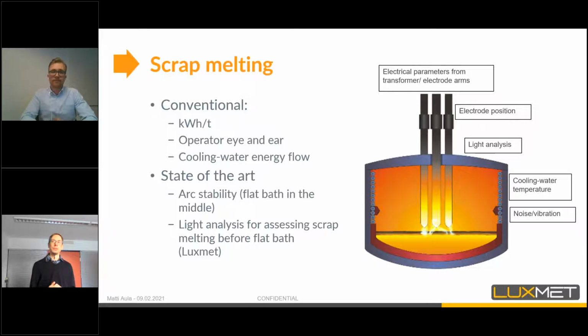Yeah. And also, the state-of-the-art methods, or the best available systems, let's say, many people use these arc stability parameters to assess the scrap melting in the furnace. Because in the flat bath phase, the slag surface and steel surface start to calm down. There is not so much movement there. There is also not so much scrap falling into the arc. So because of this, the arc gets more stable during the end of the scrap melting. And this is often used to define the end point of the scrap melting, on average, on a